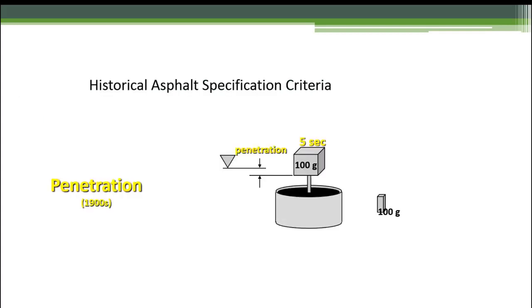Before we get into a lot of detail on that, I wanted to talk about the specifications. From the late 1800s on, basically you specified asphalt. You need some type of specification, right? Get what you ask for, get what you measure. It was called penetration grading, sometimes shortened to pen graded. And it was a simple test. You essentially had this tin of asphalt at room temperature in that cup, and you put a weighted needle on it, and in 5 seconds determined how far that needle penetrated into the asphalt sample. So the number you get in a penetration grade actually is a distance.